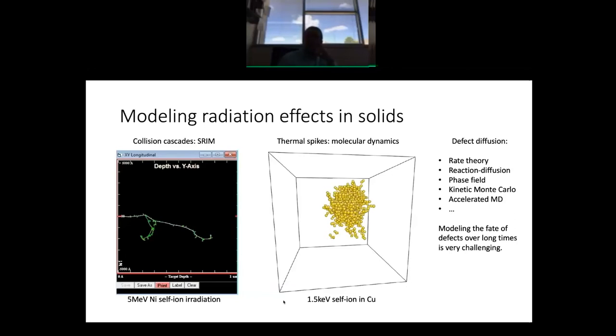And so what you see here is something like a miniature explosion, right? It happens on a length scale of maybe a few nanometers, maybe up to 10 or 20 nanometers, depending on the energy. But it's a fairly localized event. It's an event that involves lots of many-body interactions. Can't use the binary collision approximation for it, so we use molecular dynamics.